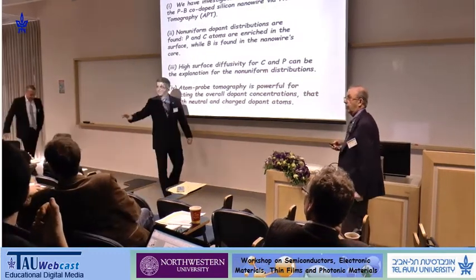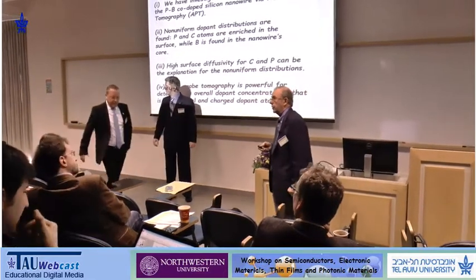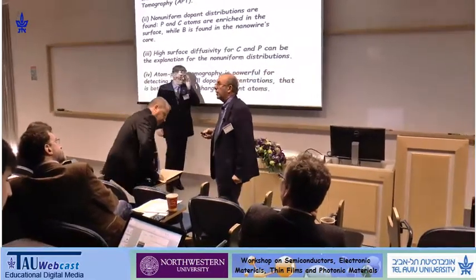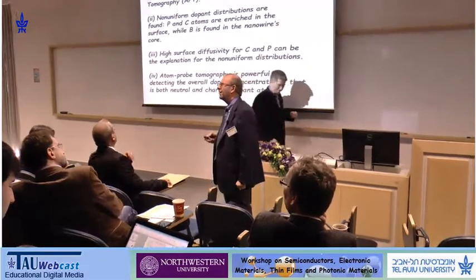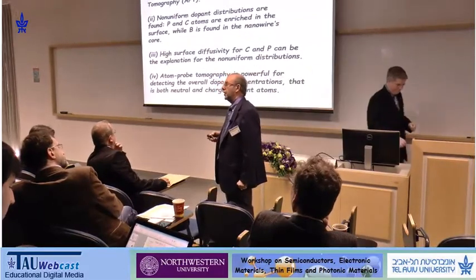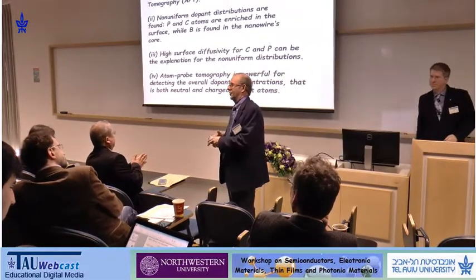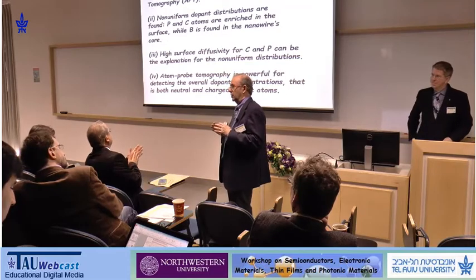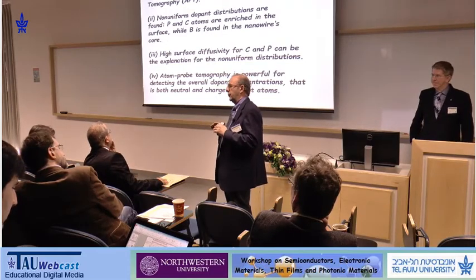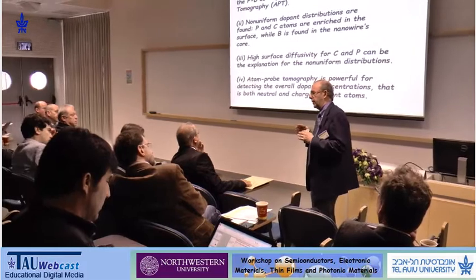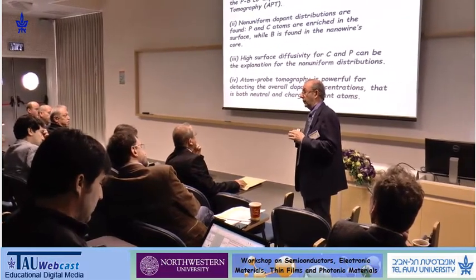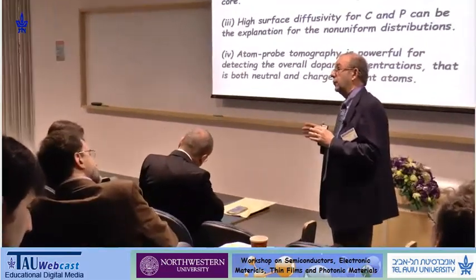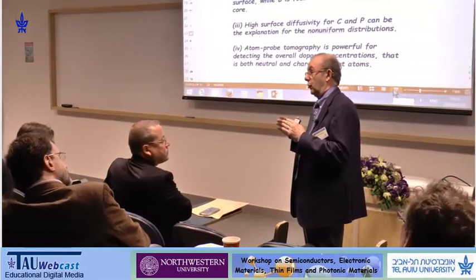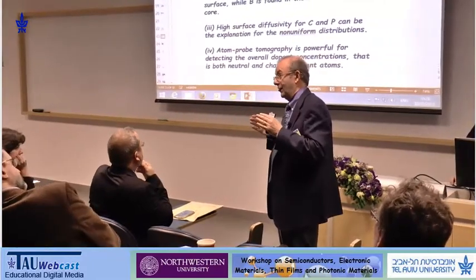So the graphene, I would assume, is atomically thin initially after growth. Yes. And yet, if you look at your carbon cross-section, it's over an order of magnitude larger. So is that an artifact of the sample prep? No, it's not an artifact of the sample. It's because the three materials, the graphene, the nickel, and the copper, have different evaporation fields, and so you get trajectories when the atoms are evaporated that tend to broaden it.